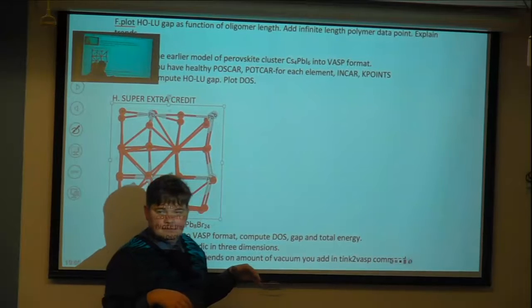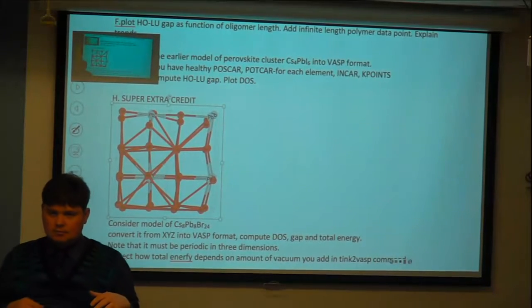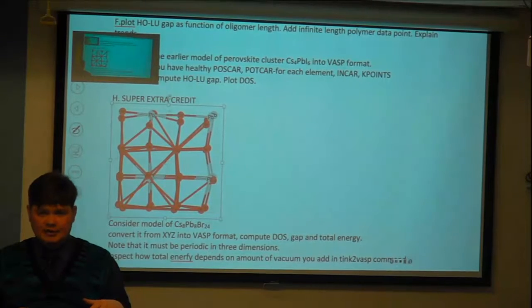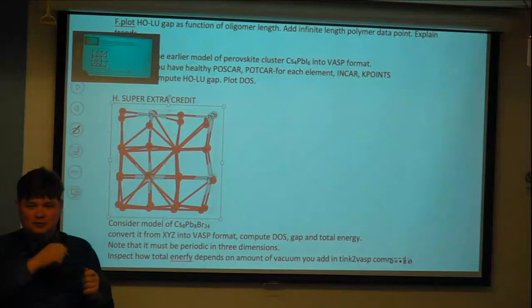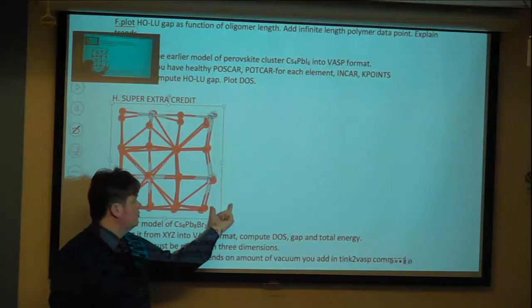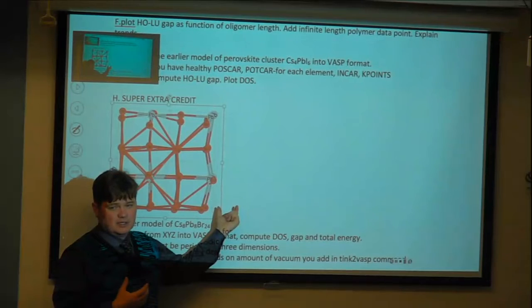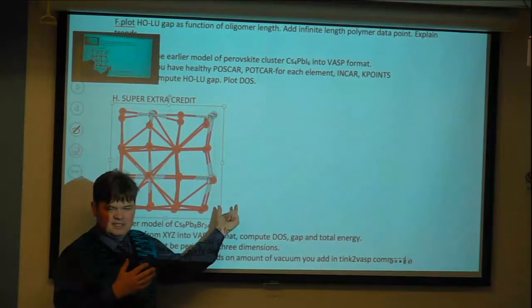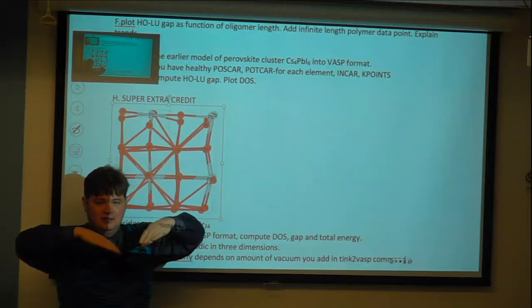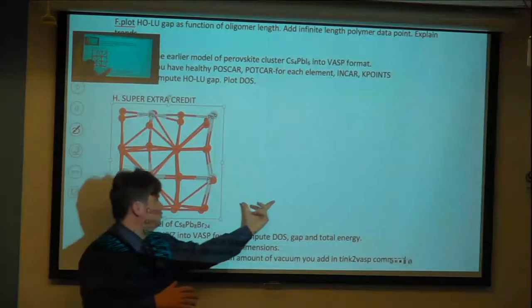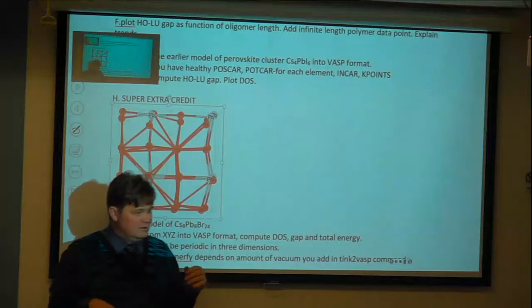So does the vacuum just put a space in between the repeating cells? Yes, adding space. Vacuum meaning you do not put any hydrogens or water, you just put empty space, but a really small amount, like a couple angstroms. And you will find out that there is a magic number, like 1.7, that will minimize total energy drastically, and all others will make it expand. If you smash them into each other, it will grow very much. If you put a lot of vacuum, it also will be a little higher.